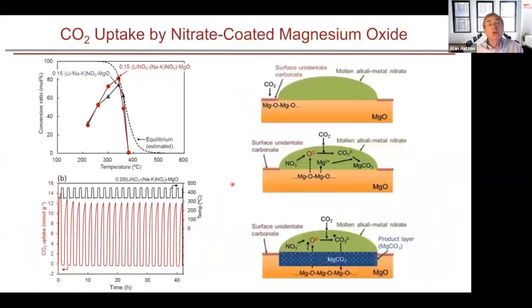This is just showing that we are looking at magnesium oxide, where we've overcome some of the many limitations that people have had in the past by having molten alkali metal nitrate as a promoter for the CO2 capture and the formation of the magnesium carbonate in this particular case. We're not the only people, other people have also been looking at this. But the important part is that we are able to operate rather stably over many, many cycles as shown here. By having the promoter here, we can overcome many of the kinetic limitations associated with CO2 capture and bring it up to the equilibrium curve. We'll be limited by equilibrium rather than kinetics in the system.